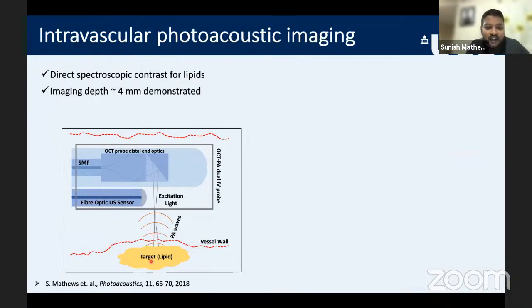One big advantage of this is that you can get specific spectroscopic contrast for a target, provided that you use the right wavelength. If you use the right wavelength at which the lipid inside the plaque is absorbing, you can generate photoacoustic waves from only the lipid region, and then you can clearly visualize the plaque area. So this is the idea of using intravascular photoacoustic imaging. And you can achieve imaging up to 4 millimeter depth.